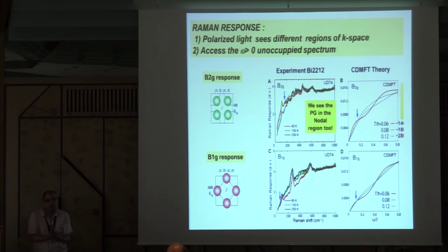In the antinode, we have a clear, well-defined pseudogap. And if you look at the Raman spectra here in the B1G that are probing the antinode, you will see that as temperature decreases, you have a loss of spectral weight. That loss of spectral weight is a signature of the pseudogap. Now, in the B2G, it should not be the case if there is no pseudogap. Well, it's known from many other members of the cuprate family that there is a small decrease. If you look, 250 is the black curve, 150 is the green, and it doesn't happen much. For the red, there is some loss of spectral weight. It's very small, but it's there.